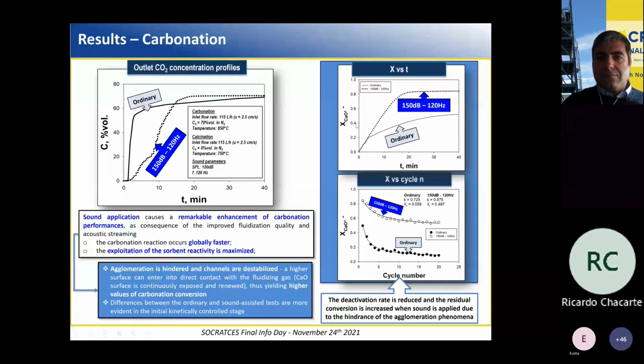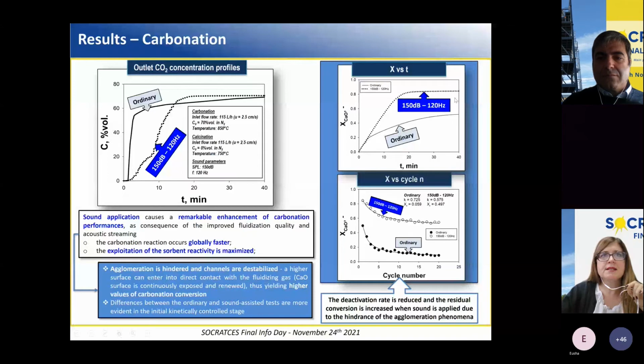Finally, here you can see the carbonation conversions as a function of the cycle number obtained during both ordinary and sound-assisted conditions. It is clear that the deactivation rate is reduced and residual conversion is increased when sound is applied. In particular, agglomeration plus sintering occur under ordinary conditions. On the contrary, when sound is applied, the agglomeration issue is solved and only sintering remains to cause the decline